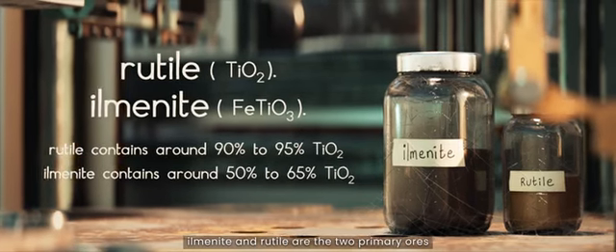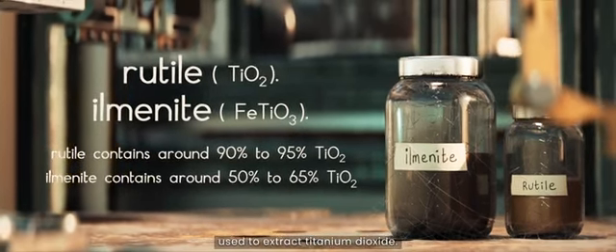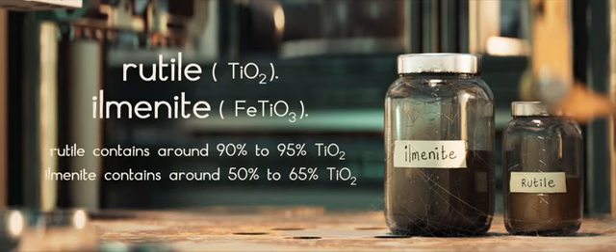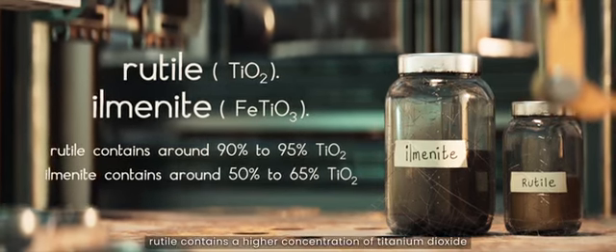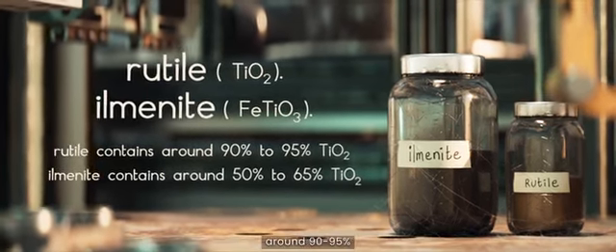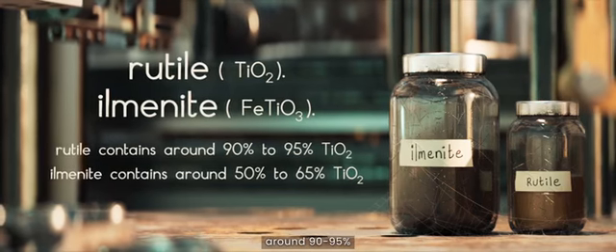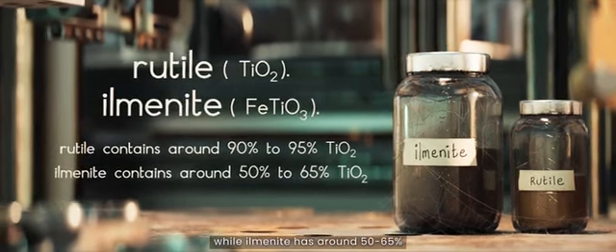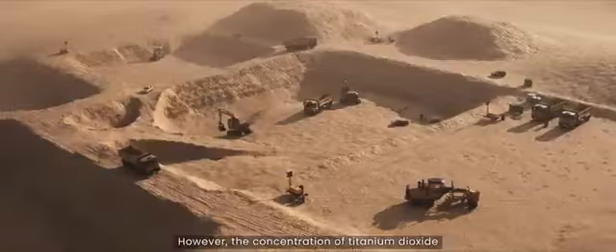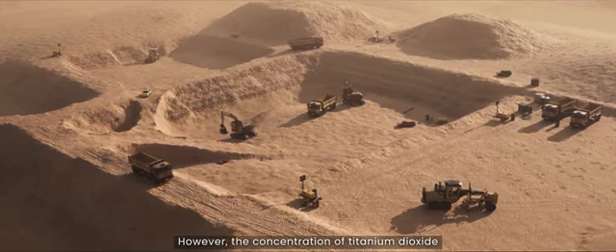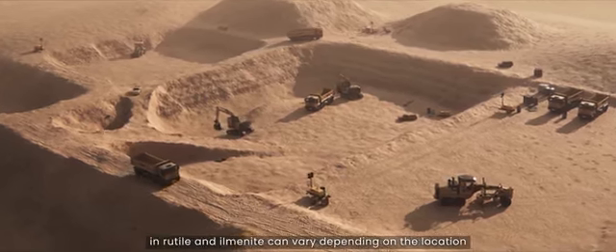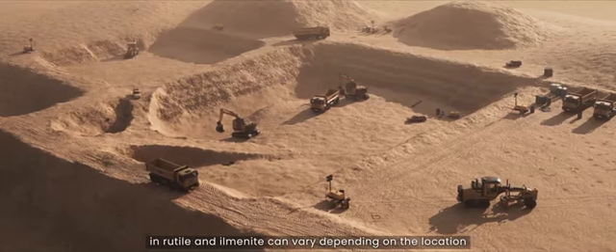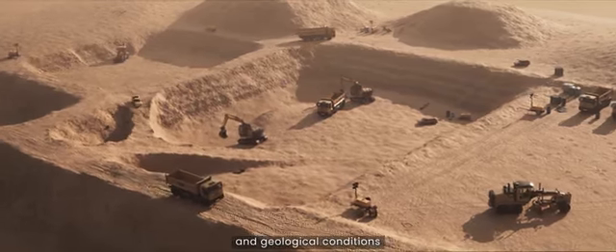Mining the ore. Ilmenite and rutile are 2 primary ores used to extract titanium dioxide. Rutile contains a higher concentration of titanium dioxide, around 90 to 95%, while ilmenite has around 50 to 65%. However, the concentration of titanium dioxide in rutile and ilmenite can vary depending on the location and geological conditions.